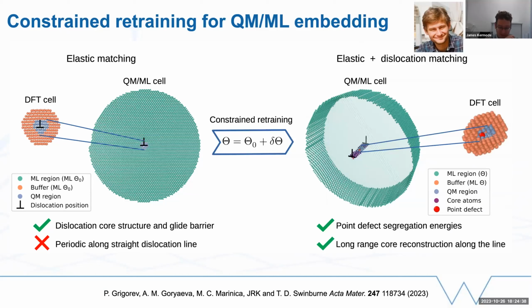But the innovation in what we did really was to update or retrain the potential so that it is actually capable of fully describing the dislocation line away from further defects. So we did a few simulations like this with QMMM, and we improved our interatomic potential so that we could have dislocation lines described correctly by the interatomic potential. And then we could look at further effects.